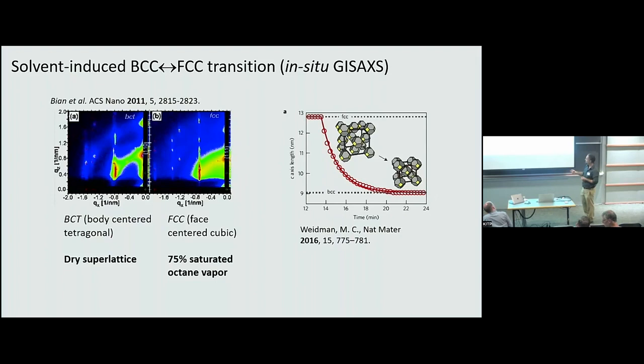And then as you start swelling the system using octane vapor, there is a transition from BCT to FCC, and this is reversible, right? So you can go back and forth. There is this other paper that is related. So in this particular case, they started with FCC and let it dry and looked at the structure of the system over time. And what happened is that you have FCC, and then there is a transition as you dry to BCT. Everything in between is actually also BCT, okay? But I think these two examples show very well that solvent plays a role and that you control the structure of the system with the solvent too.